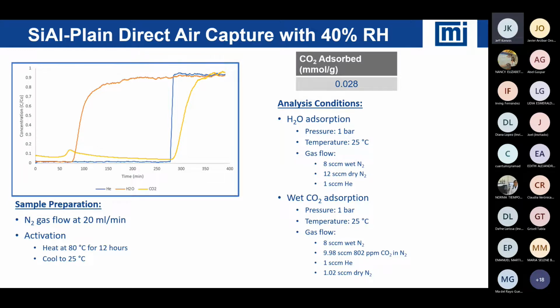Water adsorption and equilibration tends to be quite slow. So as we go down this path of looking at water, one of the typical behaviors and practices we should use is we should make sure the sample is equilibrated with water first, because that's going to be really a big driving force in precision.